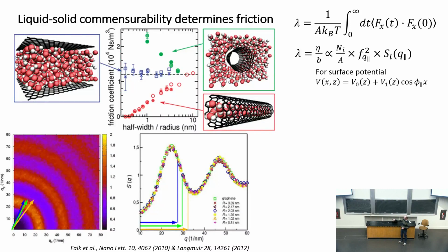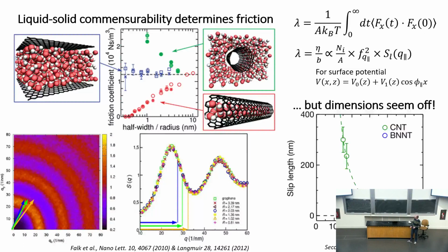For example, here the green arrow is the case for a flat graphene sheet, where it sits somewhere here. So you basically look at commensurability effects. The more commensurable your water is with your underlying surface, the more friction you will have. So the flat one is here. You put water on the inside, you'll be going towards this point here. So this goes down, friction goes down. If you put water on the outside, you'll go up this slope. So that's what's been suggested.